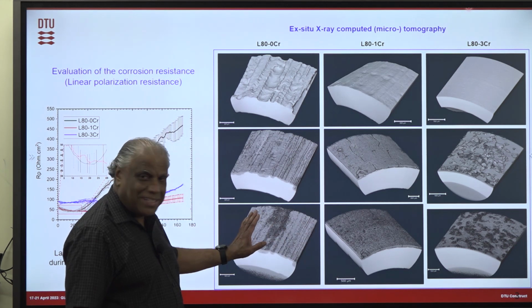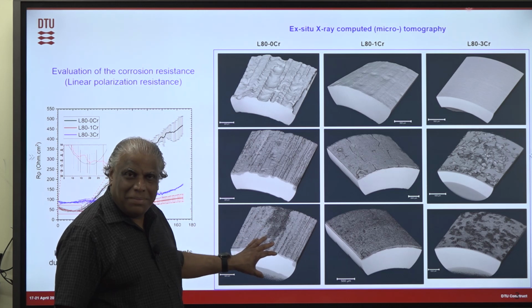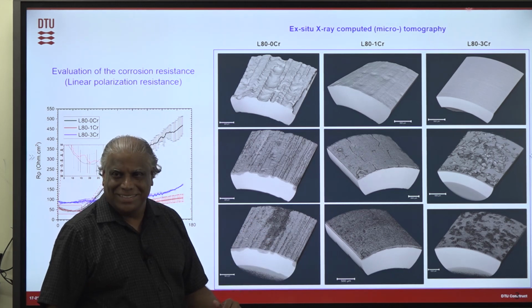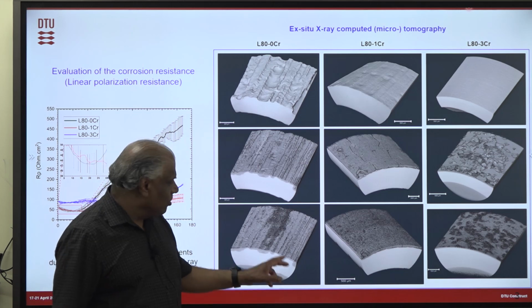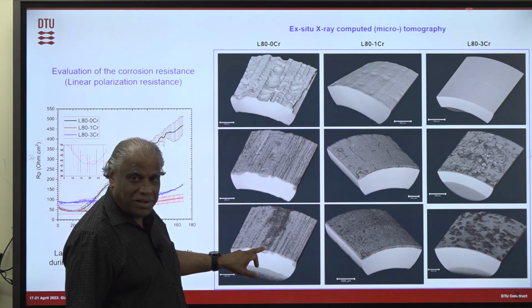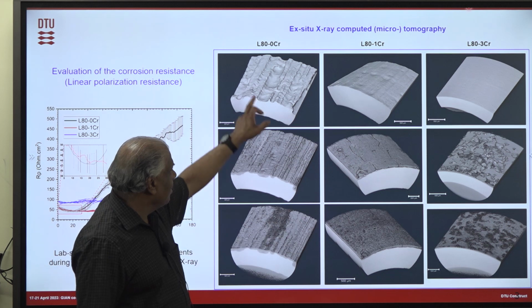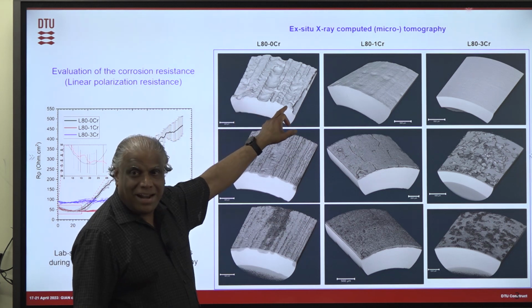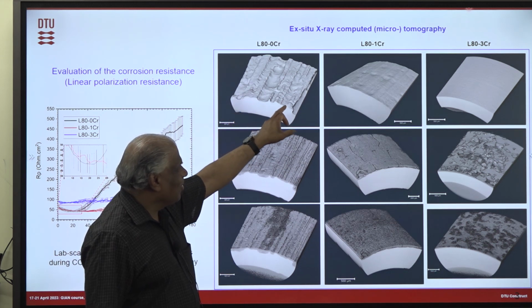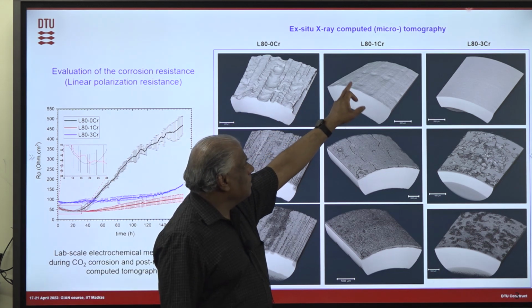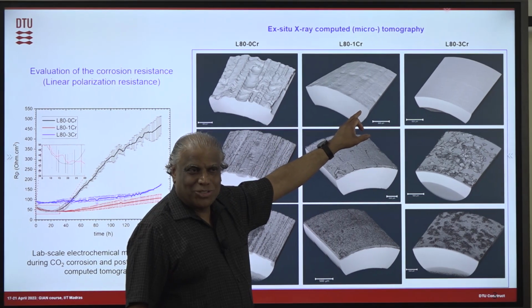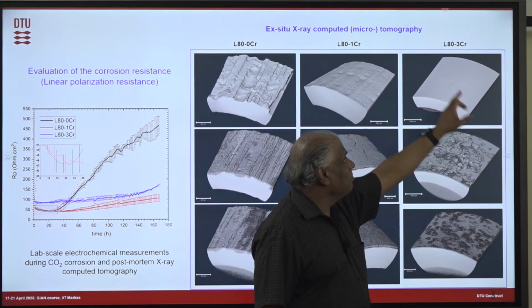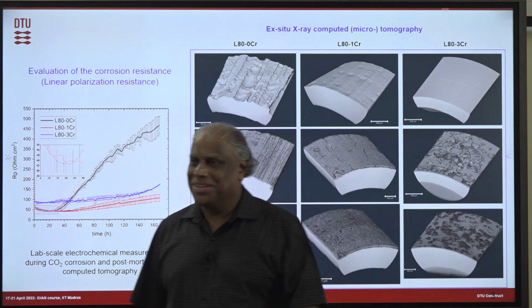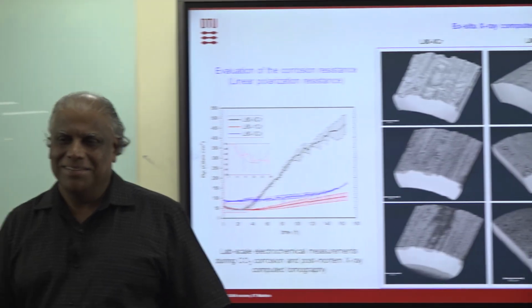There was corrosion product scale, but in this image, by image analysis, we can remove that corrosion product. So this is after removing the corrosion product. When you remove it, this is the metal underneath, the way it is corroded. With 0 chromium, you see there is a lot of corrosion, and with 1 chromium it becomes much more smooth, because chromium is protecting, and it becomes very smooth with 3 chromium. Just by looking at it, you can understand the advantage of adding chromium, even 1 chromium, into the alloy.